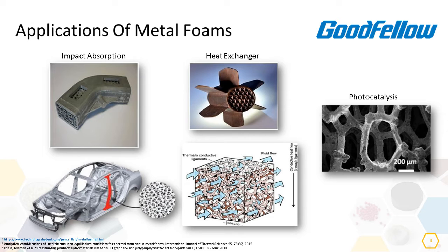Goodfellow nickel foam in a photocatalysis experiment. The foam has been used as a scaffold template for graphene to produce a graphene foam. This 3D hybrid material shows interesting perspectives as a charge transfer material, and that's a very innovative application, I would say.